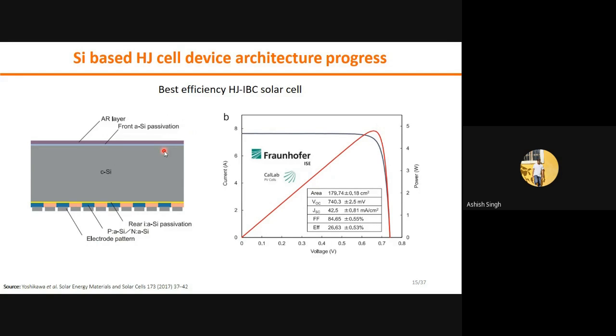So due to this, they could make the highest efficiency solar cell, and they got a current density of 42.5 milliampere per centimeter square, and as per the Shockley-Queisser limit we can go up to 44 milliampere per centimeter square. So they could reach close to this. Yeah, so this looks like a very promising candidate for heterojunction solar cell application, and they made commercial modules.